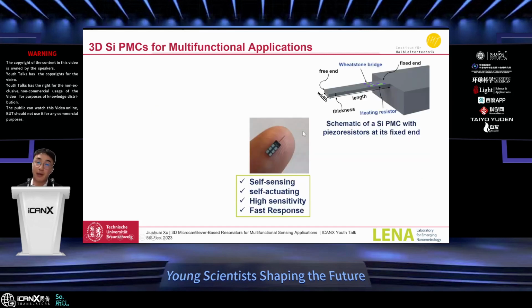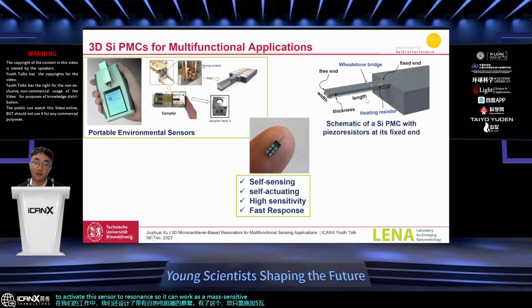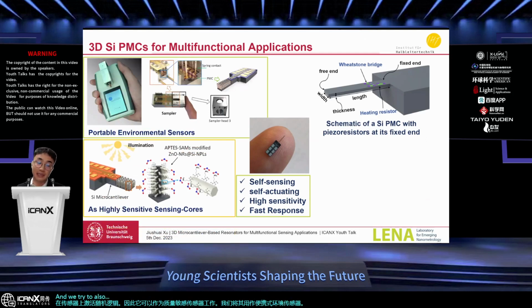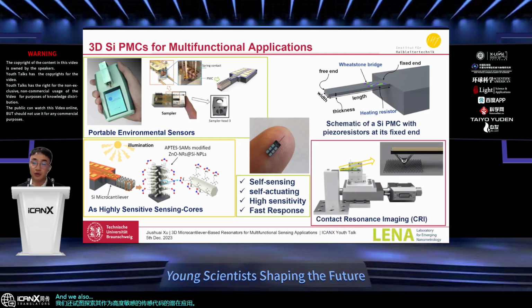So here we come back to the microsensors. We have to remember all of this fabrication happens on these very small microcantilevers, and in our work we designed the cantilever with self-heating resistors. You can just apply 5 volts to activate this sensor to resonate, so it can work as a mass-sensitive sensor. We use it as a portable environmental sensor, and we also explore its potential application as a highly sensitive sensing cores. We also try to use it for contact resonance imaging to check its multifunctional applications.